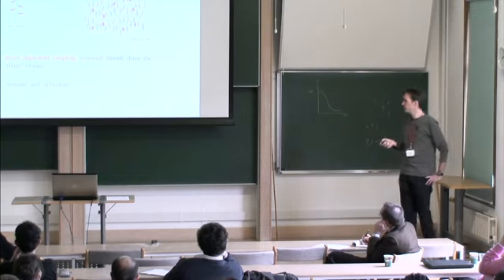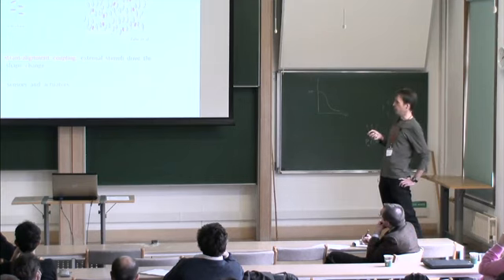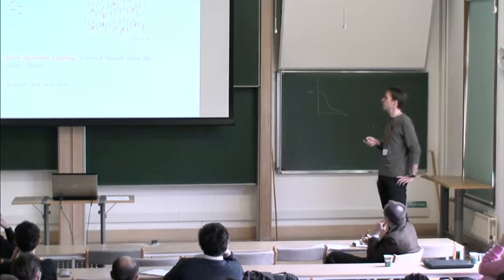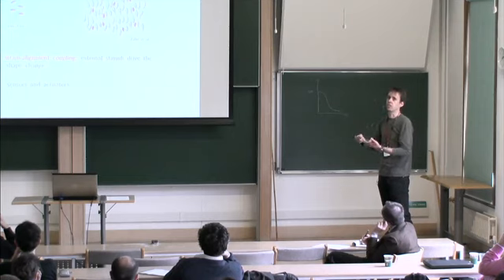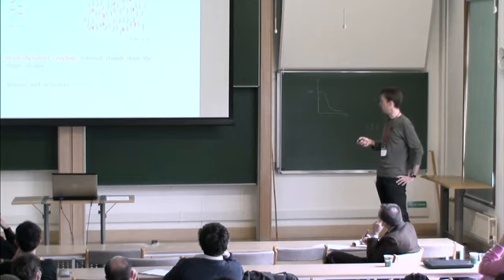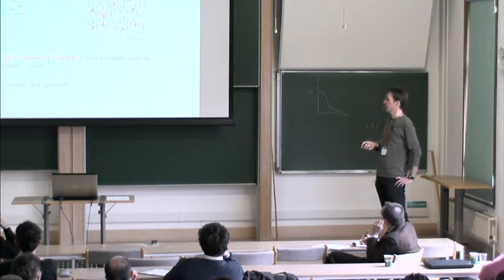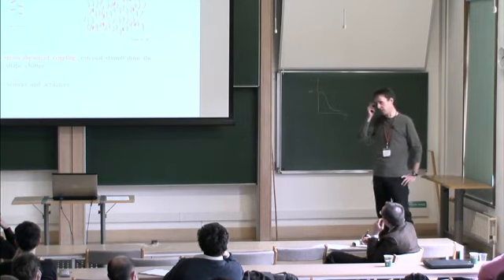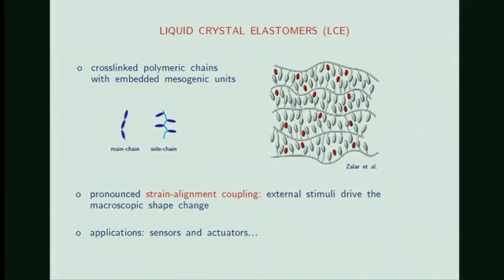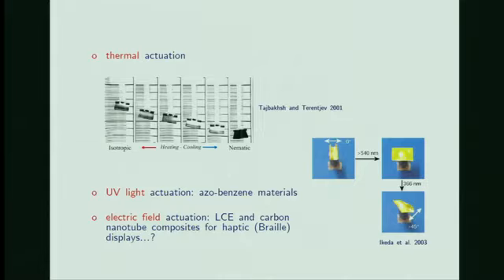What's important in these materials is that such a macroscopic setup will yield a pronounced strain alignment coupling. The external stimuli that are able to act, for example, on the mesogenic molecules will drive a macroscopic shape change in your system. One can easily think of several applications of these systems, typically as sensors and actuators. As for actuation, one of the possibilities is to actuate via temperature changes. Here you can see a nice contraction of your elastomer on heating.